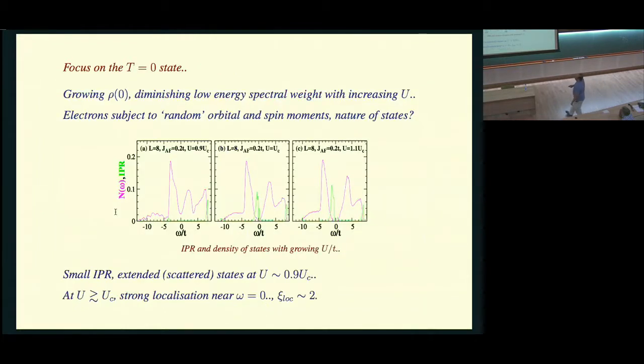We're almost there. So this is to bring the focus back on the Anderson-Mott story. What is happening to the electronic states here? I mean, is there anything different or more interesting here compared to what we saw in the parent Hubbard model? We noticed something unusual, that the optical and transport gaps in this, not the materials, in the calculation, seem to differ. You seem to find a density of states where the optical conductivity doesn't pick up any contribution in a certain window. So we went and computed the IPR, the inverse participation ratio, supposed to be indicative of the degree of localization. So if you're in the metal at 0.9 Uc, and I am supposed to be looking at omega equal to 0, the Fermi level, the IPR is small, suggesting that you have extended states.